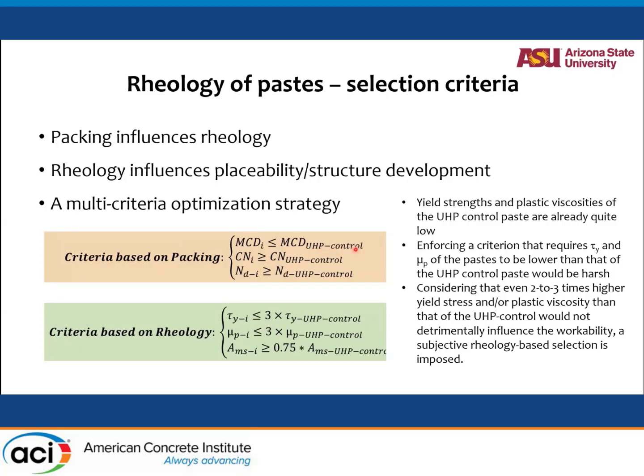The UHP control paste is a high-performance concrete designed with only cement, and plenty of cement at that. And you know that particles cannot be packed as efficiently in this case, which means that to get the same properties in a pure cement UHP as compared to something with multiple binding materials, you obviously had to have a much lower water binder ratio and a higher use of admixture. So those are taken into account in how we did that.